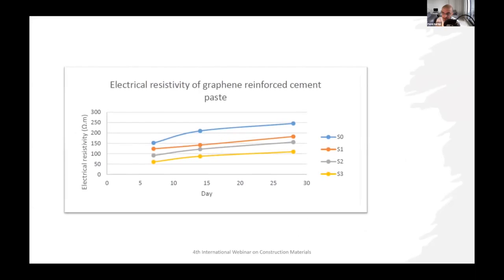As expected, the samples with a higher portion of graphene oxide recorded a higher electrical conductivity, or in this case, lower resistivity. However, it is not rational to increase the portion of graphene in the mix due to many reasons, the most obvious one being the cost, and the second reason that comes to mind is the uncertainties around the corrosion rate. Regardless, being able to produce graphene oxide is being considered a technological advancement for the material industry.